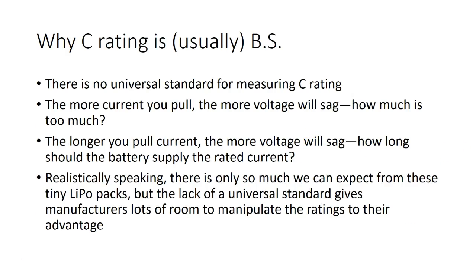Here's the one that I think is still ripe for abuse, and that's C rating. C rating is the amount of current that the battery is rated to provide. And the thing is, there's no standard for calculating C rating. What would a C rating standard look like if it existed? You would say the battery will provide this rated current for five seconds with no more than 0.3 of a volt drop.